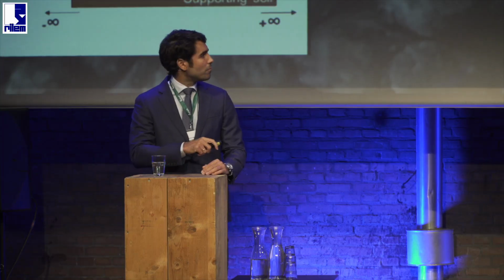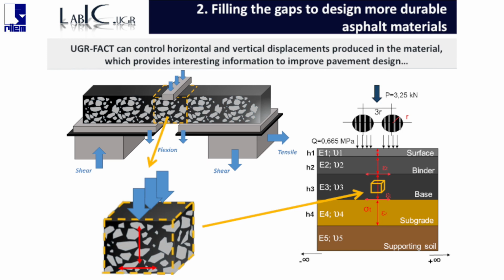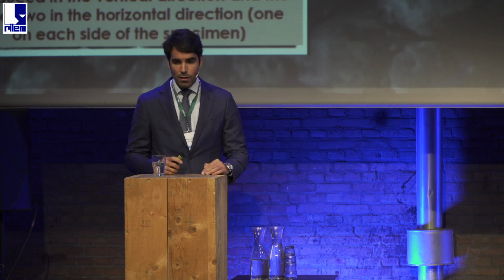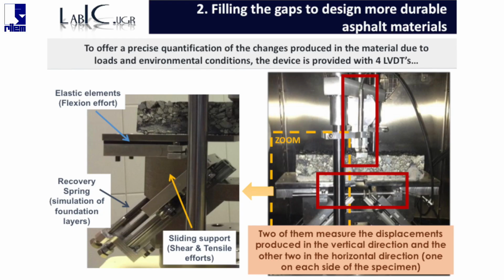In addition, it offers very valuable information for improving asphalt material design in a structural way, because we record every horizontal and vertical movement produced in that volume due to different types of load and base characteristics. For this purpose, the UGR FACT is provided with 4 LVDTs. 2 of them measure the displacement produced in the vertical direction, and the other 2 measure the displacement produced in the volume in the horizontal direction, 1 of them on each side of the specimen.